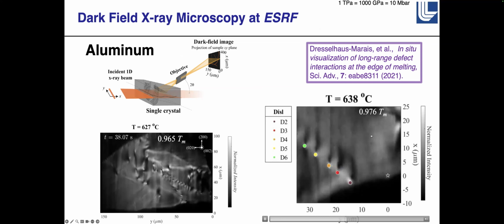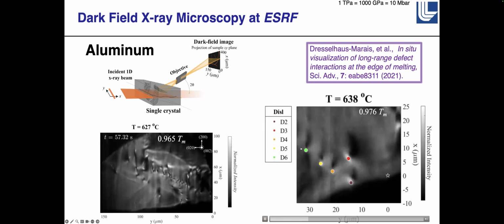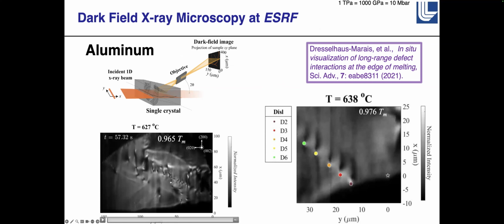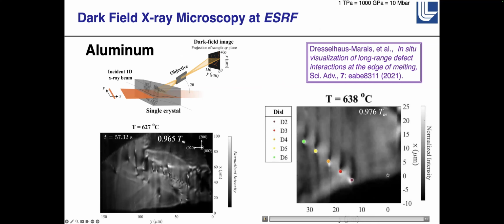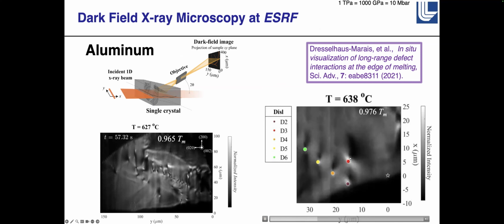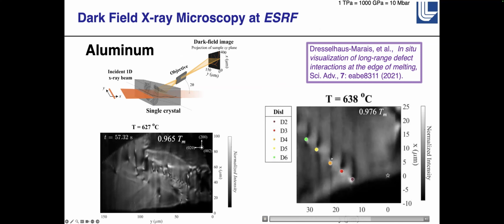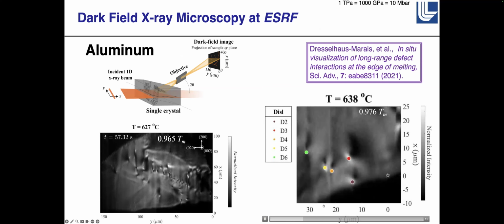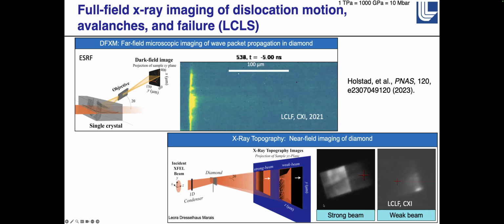One of the things it does as we went a little bit higher temperature, you can see these dislocations moving, and they form this array, which you can see starting to form out here, or I think it's this one. But you can see a dislocation inserting itself into a linear lattice of dislocations, which I think is really neat. And we would love to be able to do this dynamically.